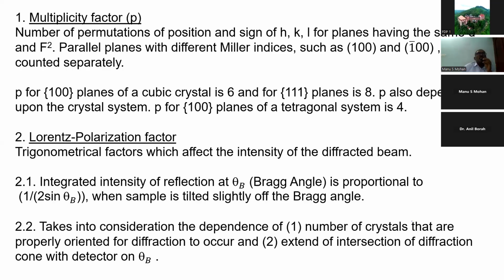In cubic structure, 100, 010, and 001 all have the same d-spacing. But once you go to higher crystal systems like tetragonal, monoclinic, trigonal, or orthorhombic, they are no longer the same, so there the multiplicity is less. When your specimen has 100, 010, or 001, all these can contribute to the same peak, not multiple peaks.